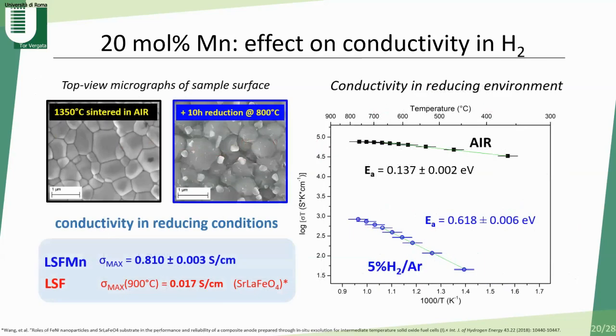We also measured the conductivity in hydrogen. As we can see, the conductivity is sensitively decreased, but the value is still acceptable to be used as electronic conduction at the anode side of SOFC. Here is the comparison at the same temperature of the conductivity with the undoped sample. There is 1 order of magnitude of difference. So it is redox stable, and it is electrically conductive enough.